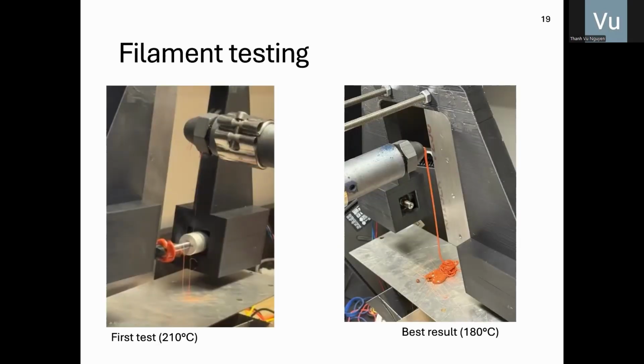And this is when we tested the filament. As you can see in the picture, on the left, we tested with 210 degrees Celsius, and the filament comes out watery and not consistent. But when we lower it to 180 degrees Celsius, the filament comes out as we desire. The thickness coming out of this barrel is 1.75 millimeters, which is perfect.